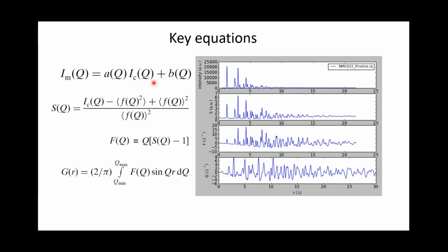And the PDF, in fact also X-ray diffraction, only uses this fraction of the outgoing X-rays, which comes from the coherent and elastic scattering. So that's the information we need, and only this part really relates to the structure information. But the measured intensity does not just include this part. This part is dominant, but it also has some other contributions, for example this B(Q).